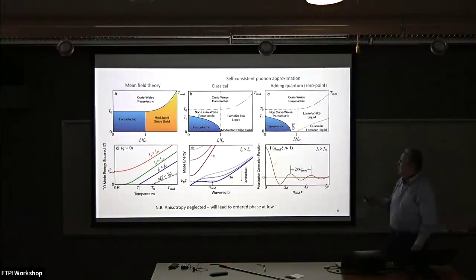Right. So then, if I turn on quantum mechanics, this long range, so the correlation length will grow and grow and grow. But eventually, I'll start spinning around in this well just because of quantum fluctuations. It's just zero point. It's not tunneling or anything like that. I've just got zero point occupancy of all of these modes. And that zero point occupancy would be enough, actually, to prevent the establishment of long-range order. Is it clear that there are no higher order terms that pick a certain crystallographic direction for the modulation? Absolutely, so there are.